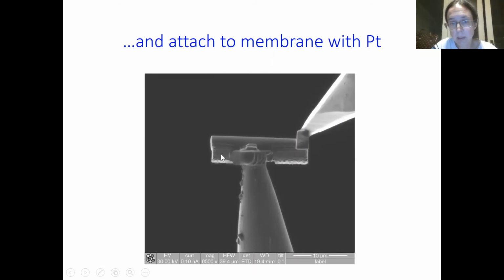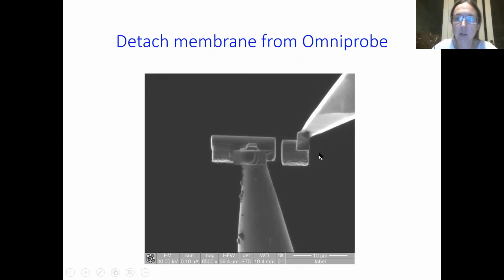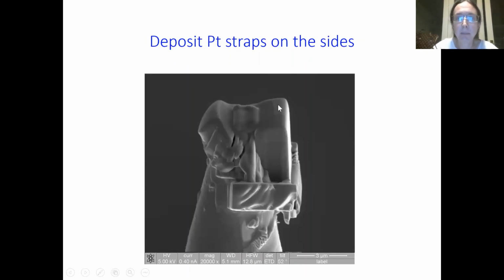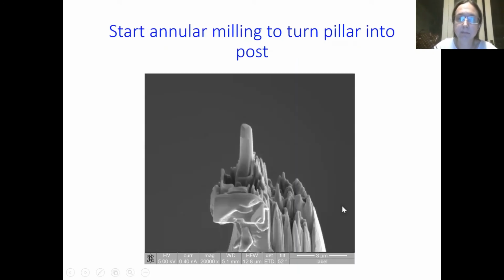And across here is my platinum strap that I've deposited using the ion beam, which I've now used to glue or sellotape the membrane to the steel post. And I can chop the omniprobe free. I have to kind of clean it up before somebody else can use it, get rid of the bit that's still attached. And then we're going to mill a square post of our original gallium nitride sample, strapping it down very nicely with platinum so we'll get electrical connection.